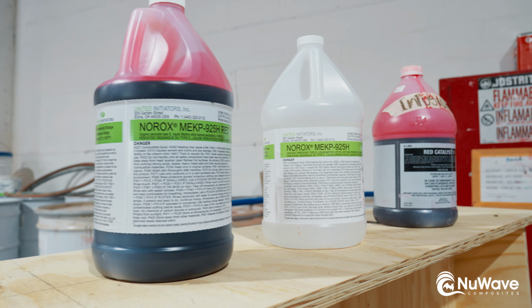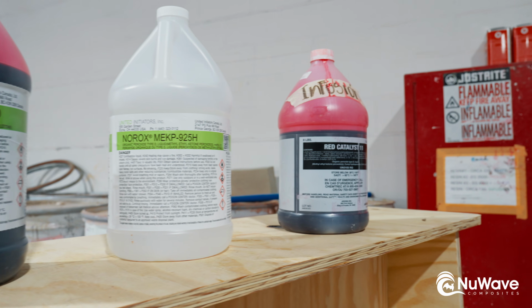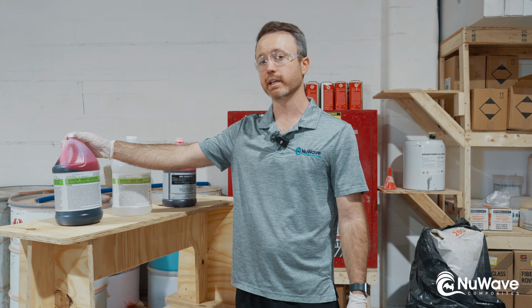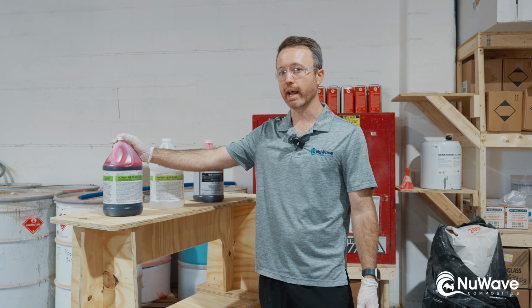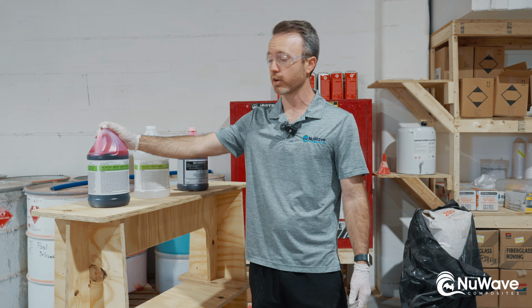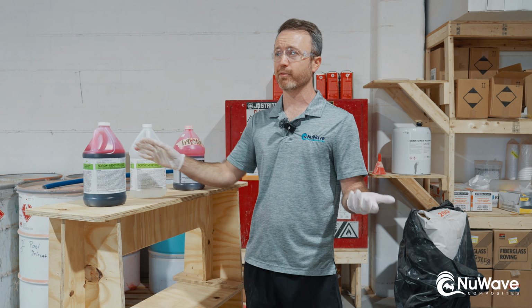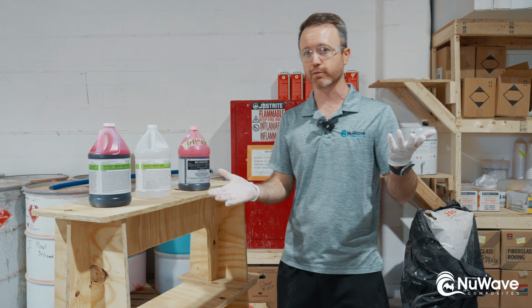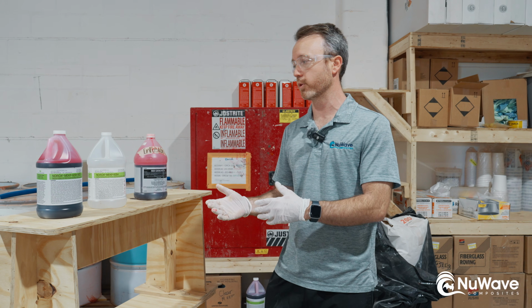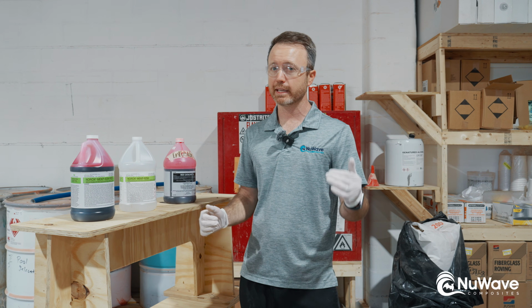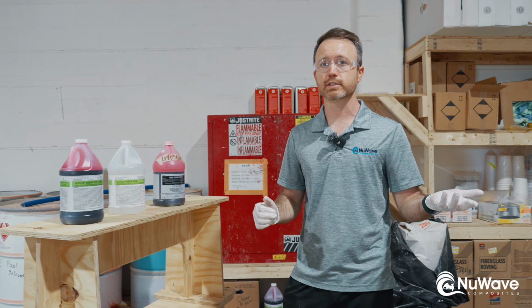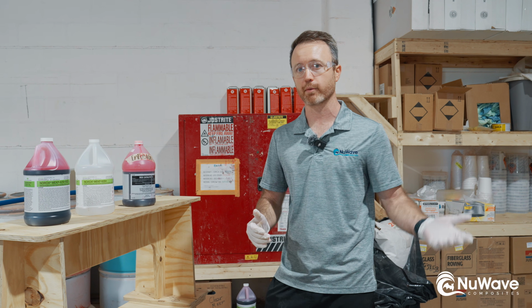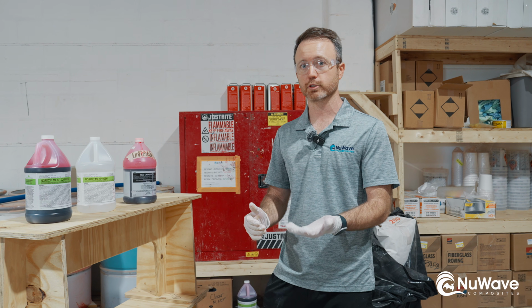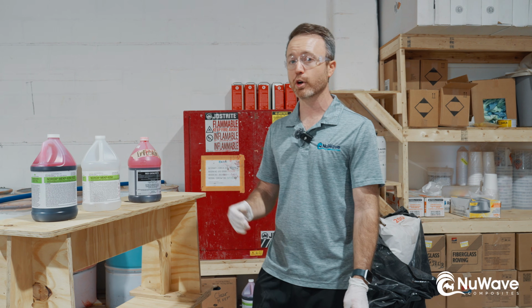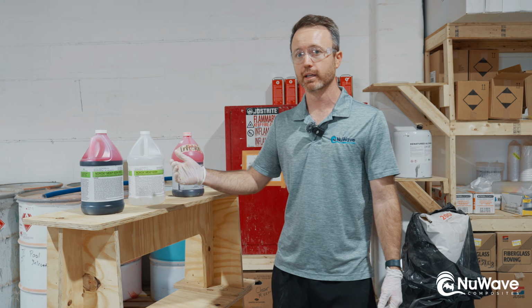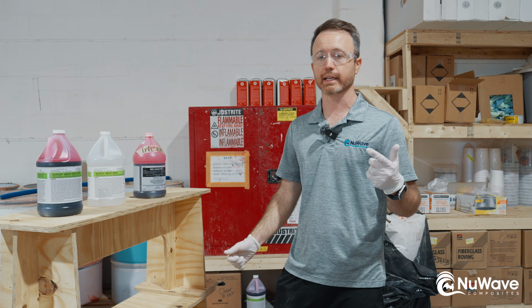So that's really the 3 catalysts that we use. And in general, these are put into your resins and gel coats in a really low amount. You really don't want to ever go below probably 1.25 on your resins, and you don't want to go above maybe 2.25. There's really a sensitive range where it's going to work well for you. If you don't put enough, it may look like it's getting hard, but chemically it's not cured, and the cross-linking that needs to happen for that resin to form a good structure just isn't there. And if you go too high, you can have problems as well. You can get brittleness and cracking, and again, cure issues.